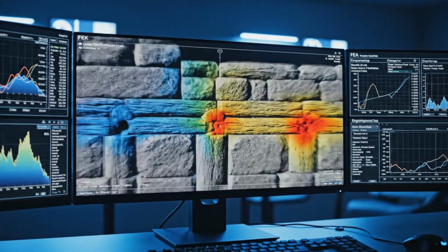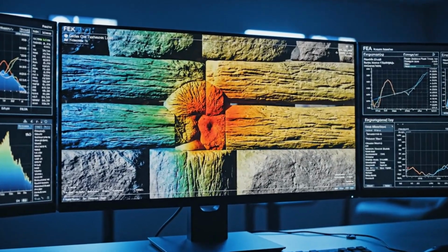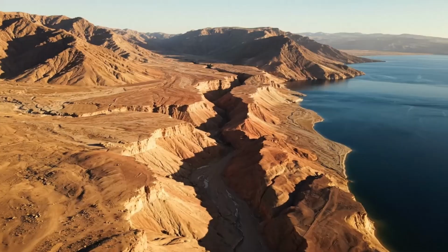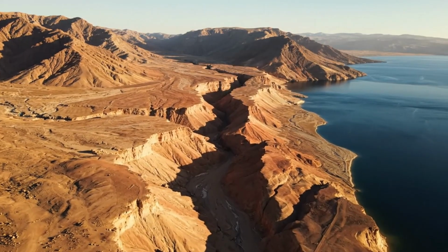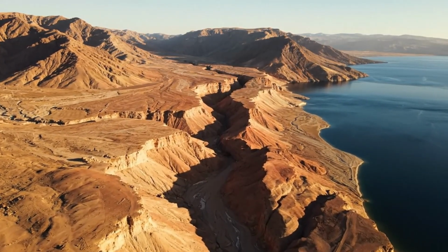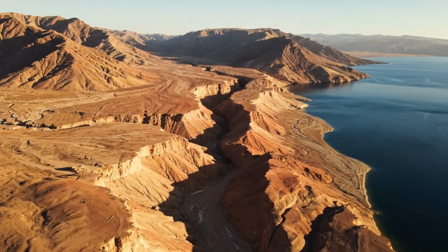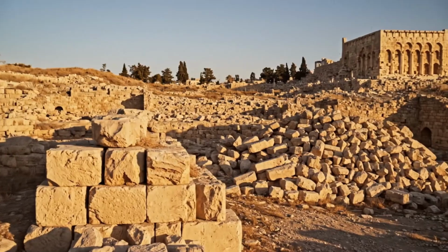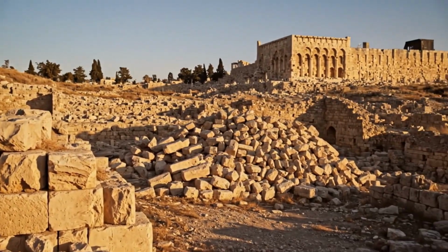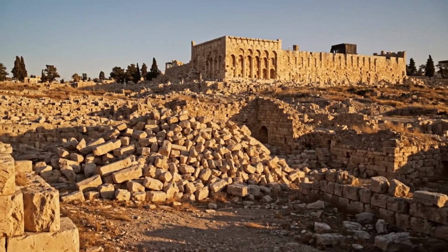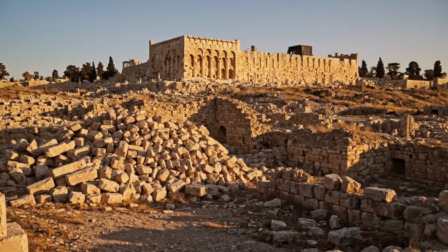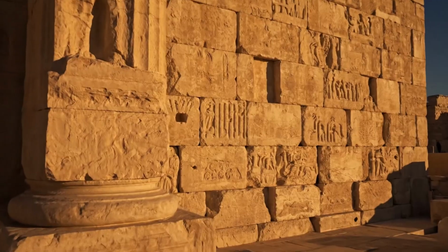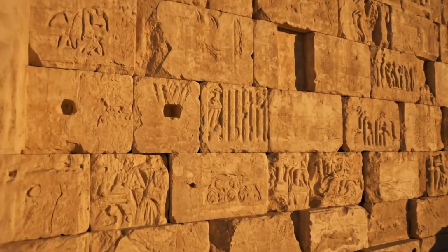The timber courses interrupt that path. Wood compresses and rebounds. It absorbs lateral energy through micro-deformation at the timber-stone interface, distributing seismic load along the full length of the course, rather than concentrating it at a single failure point. Modern engineers modeling this system with finite element analysis have calculated that the timber courses reduce peak masonry stress by 15 to 40% depending on earthquake magnitude.